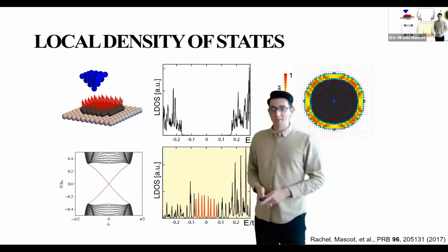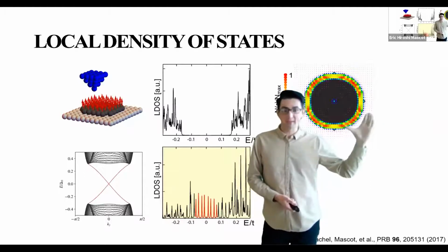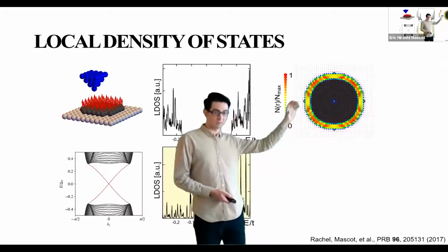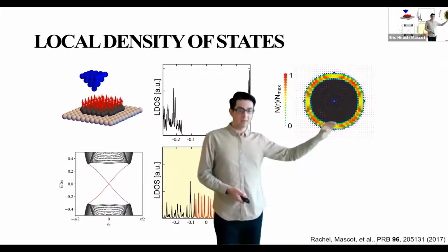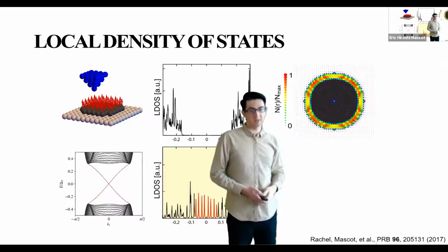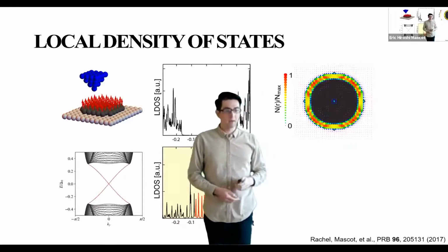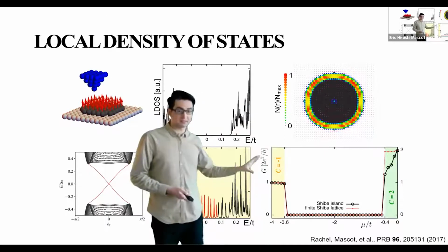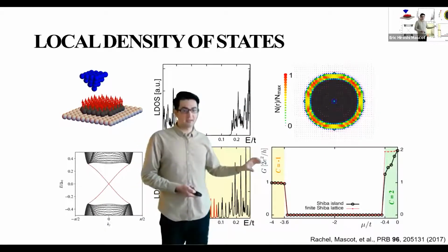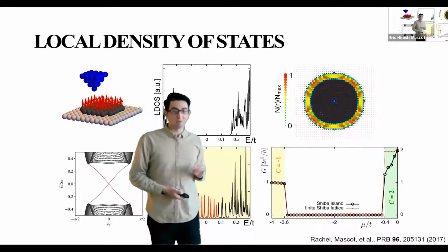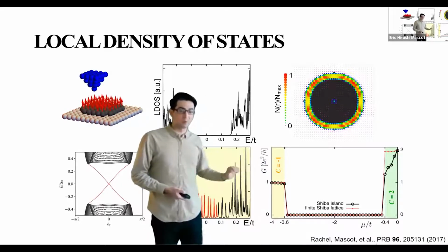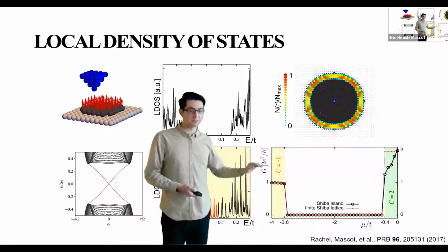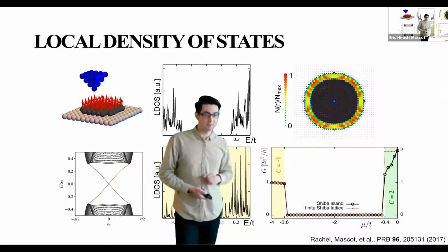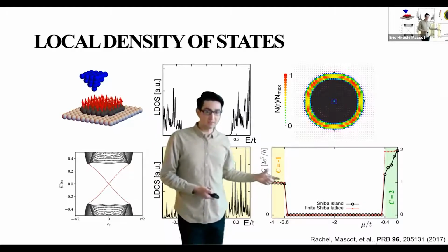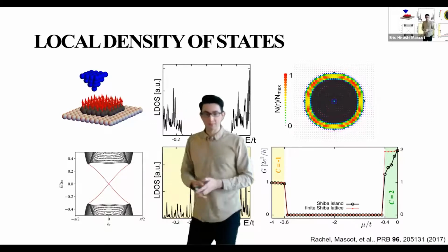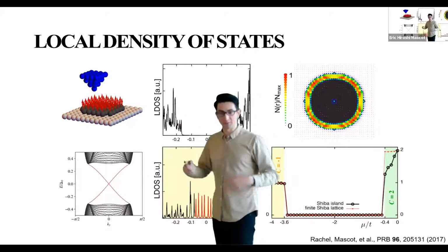Okay. And if we look spatially at zero energy, what we have is our Majorana zero mode, and it's localized to the edge of our magnetic island. Furthermore, we can calculate the conductance. This is dI/dV, what would be measured in an experiment. And we find that the conductance is quantized, and it's proportional to the absolute value of the Chern number. So for C equals 1, we have this one edge band, but for C equals 2, we have 2 of these, and so we have double the conductance.